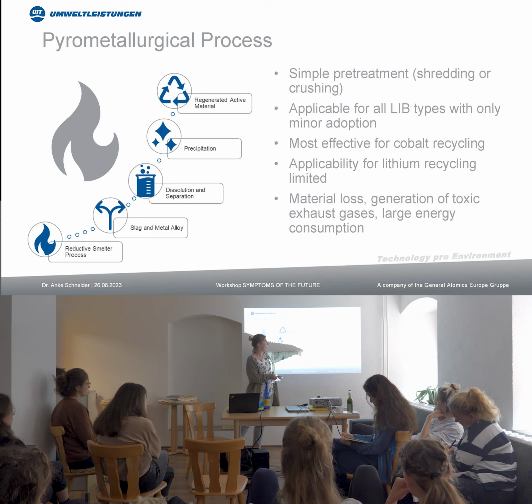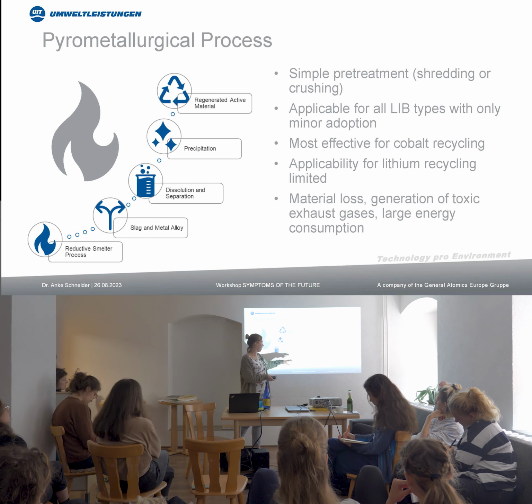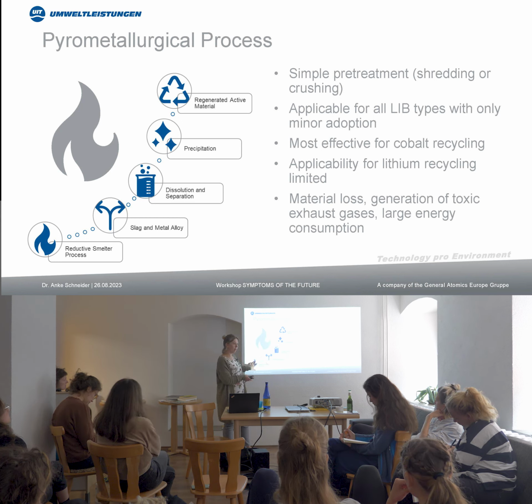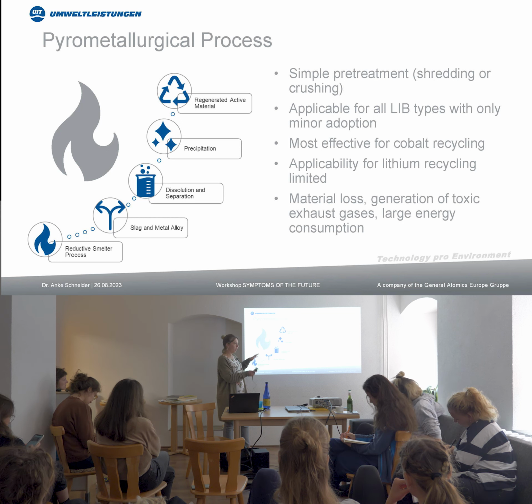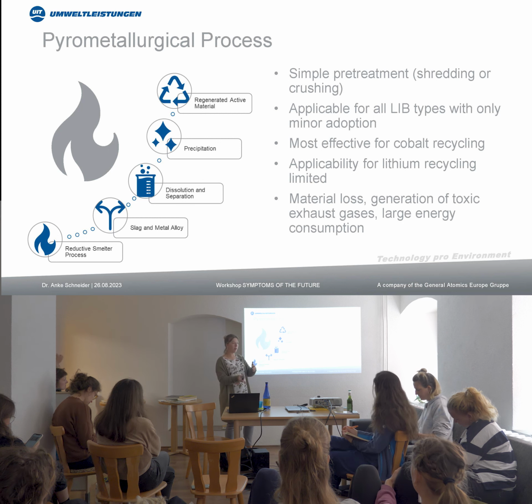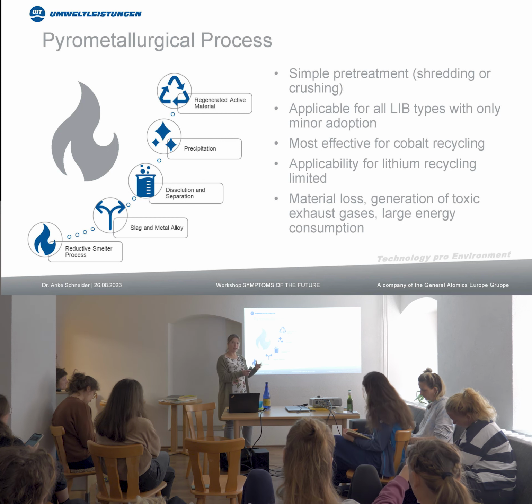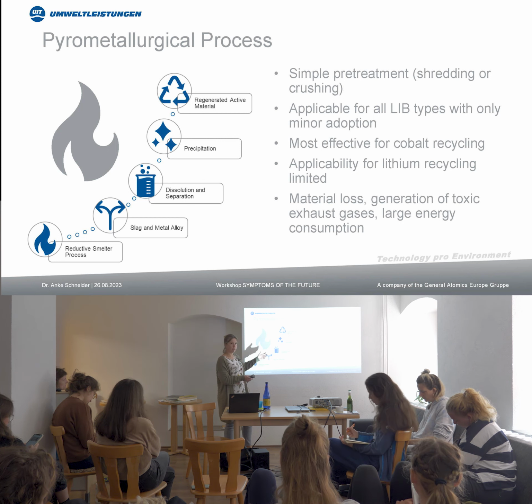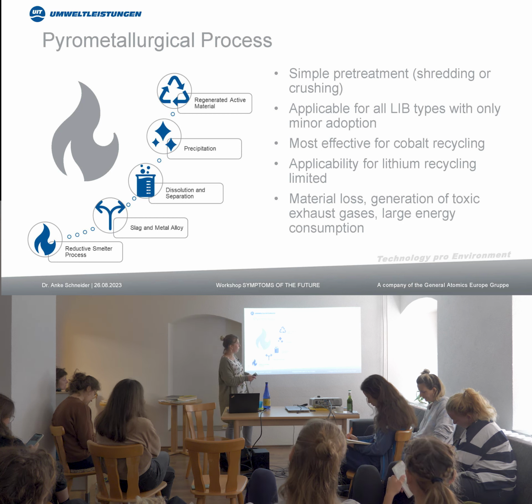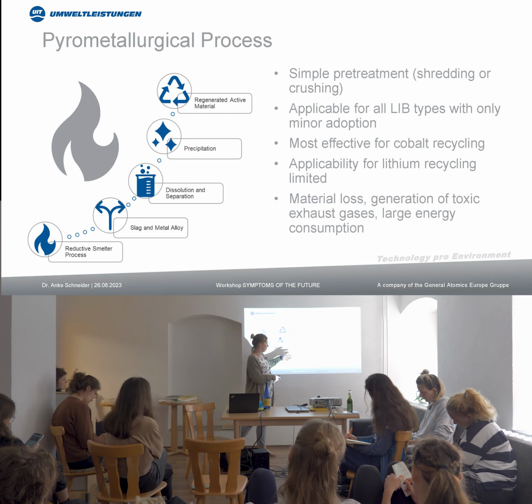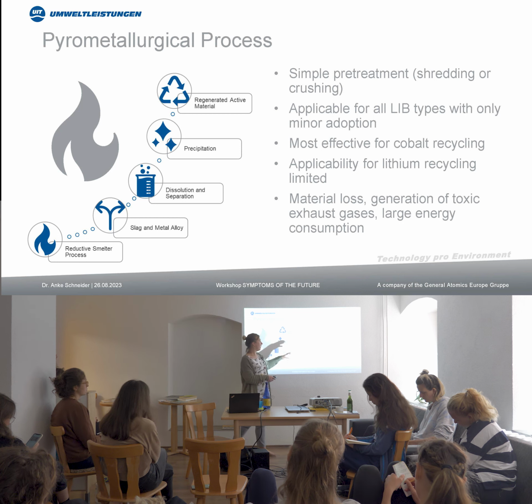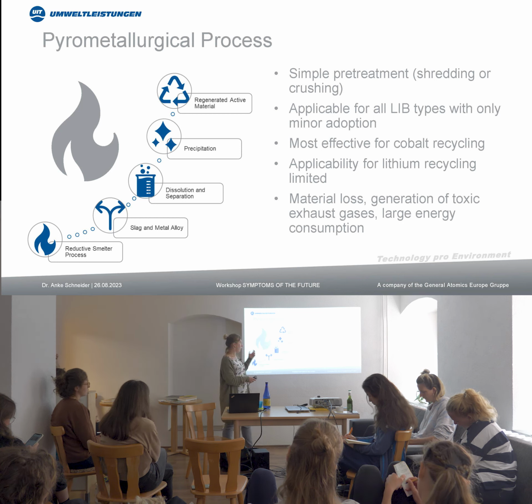And due to this, the application for recycled lithium is limited because you have losses. In the oven process, the lithium is not just in the slag, it's also in the off-gas, and somehow in the metal alloys. So it's not 100% recovery you can achieve here because you have losses in the process. And of course, besides these material losses, you generate toxic exhaust gases and you have a large energy consumption for this kind of process.